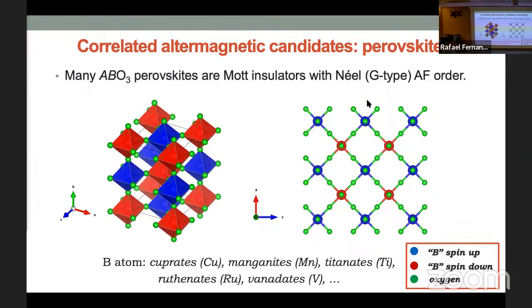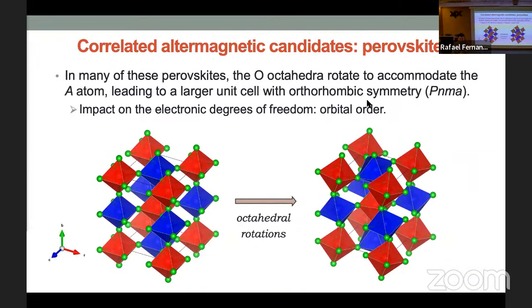We understand this well. But perovskites, depending on the size of the atoms involved, are actually going to acquire these octahedral rotations. There are lots of different patterns that can appear, but in a large number of them, it gives you an orthorhombic group called Pnma, which lowers the symmetry. Okay, what it does is that it makes the unit cell larger. So as you can see here, now, if I want to draw a new unit cell, I need to enlarge my unit cell to account for this octahedral rotation.